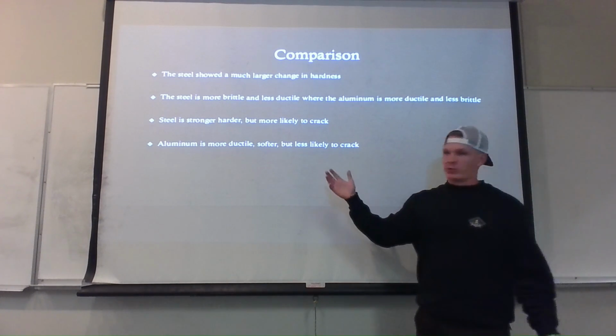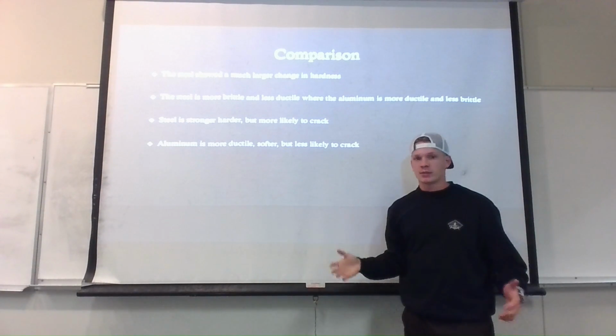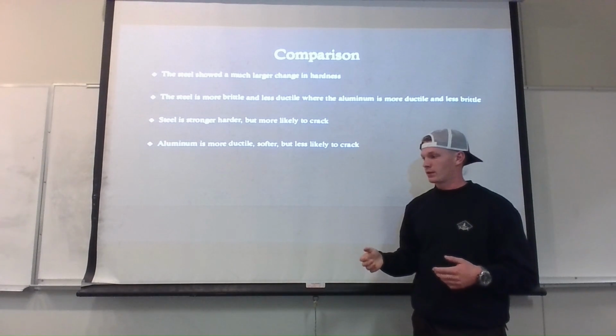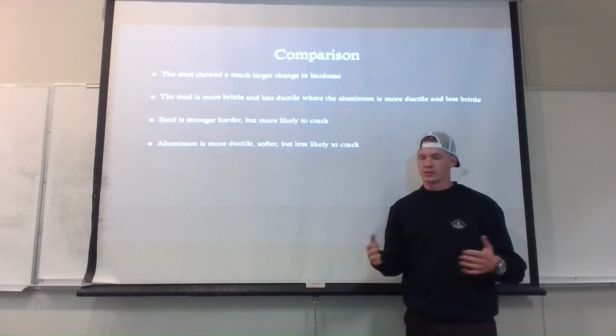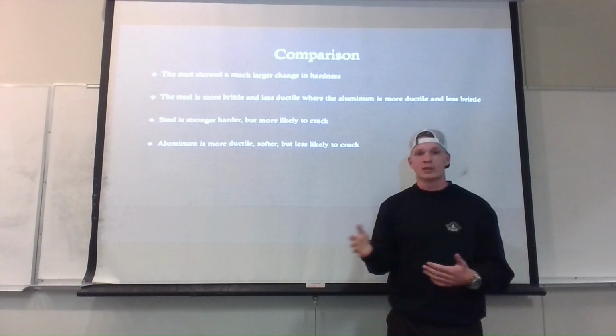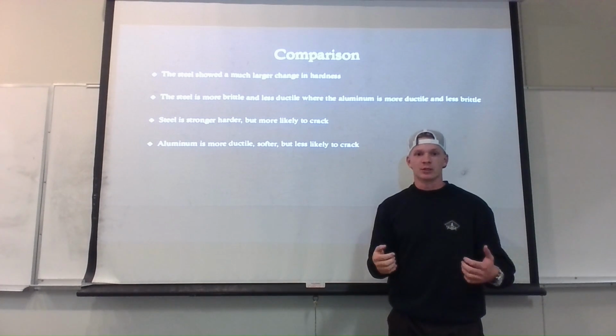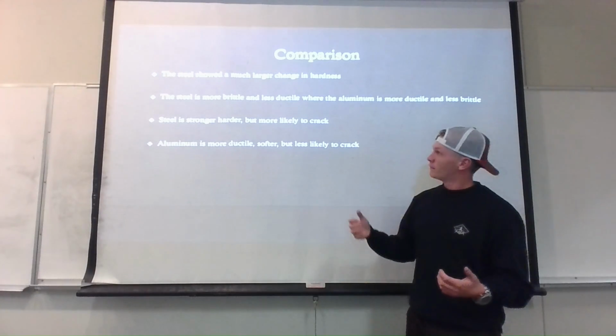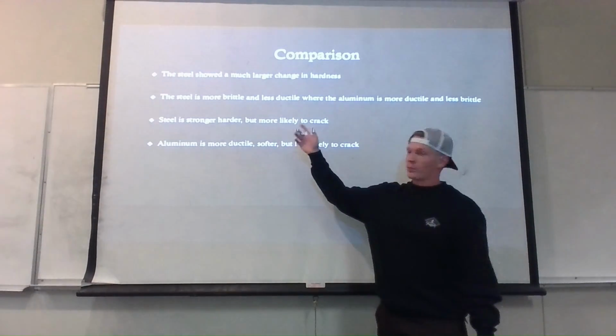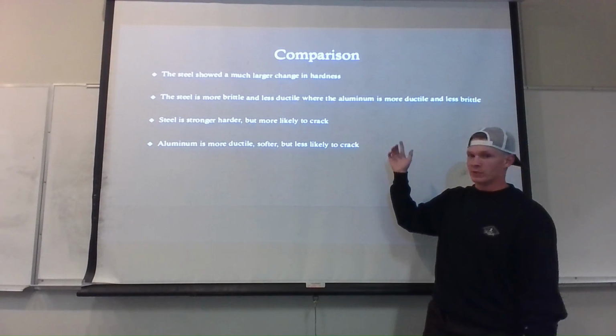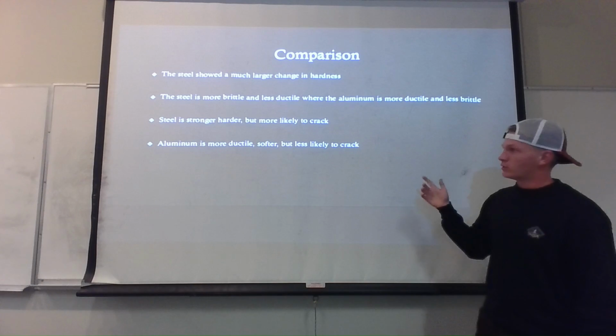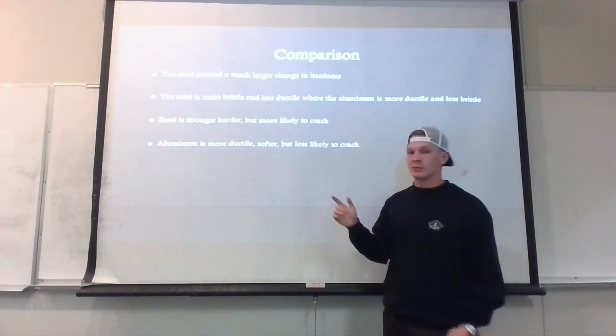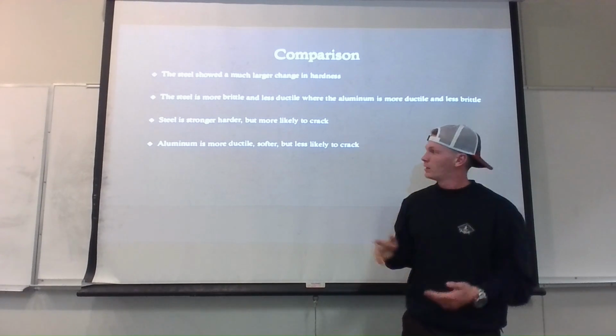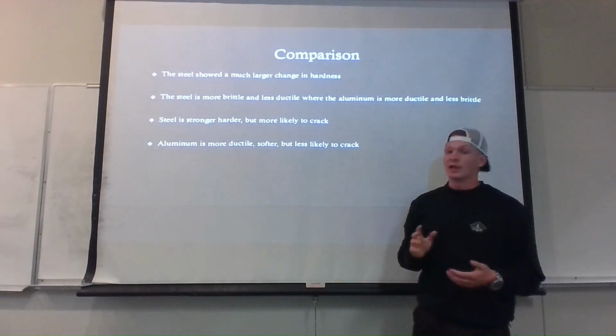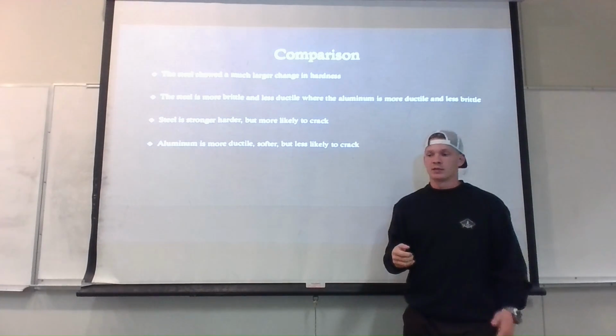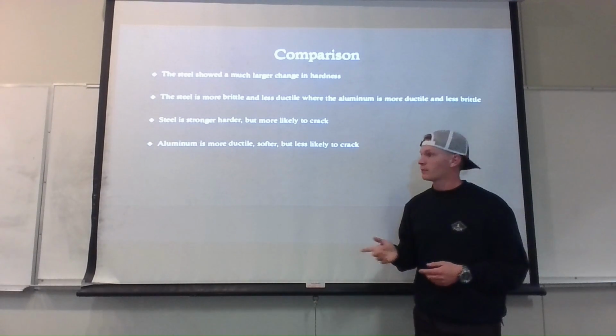So just comparing the two real quick. The steel showed a much larger change in hardness depending on where it was worked. So the difference in that hardness was, instead of roughly 1 with the aluminum, it was like 20 something. So that's just showing that cold working is making steel a lot harder than when you cold work aluminum. Because of this though, steel is going to be more brittle and less ductile, where the aluminum is more ductile and less brittle. So if you were to make a dagger with these materials, steel is going to be stronger and harder, but it's going to be more likely to crack. And then aluminum is going to be ductile and softer, but less likely to crack. So it'll be a little bit more flexible and a little bit less likely to break when you're using it.